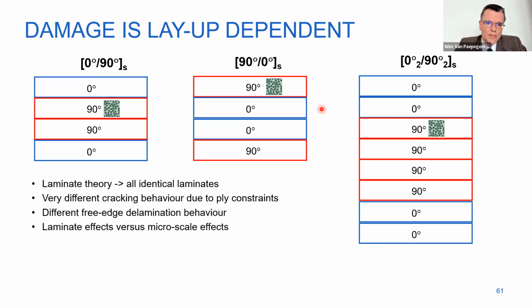Yeah, so that's something we could solve with the variational methods. The free edge delamination, you probably know, not even delamination, but just the stresses elastically. If you want to do this in finite elements, you need an extremely fine mesh. And basically in the end, it's a kind of singularity. So you have a problem and it runs for a very long time. So with variational models, we can have the free edge stresses calculated.